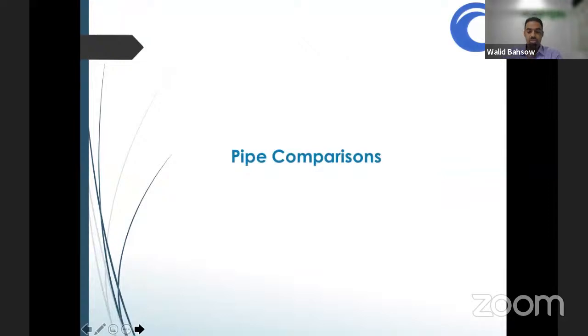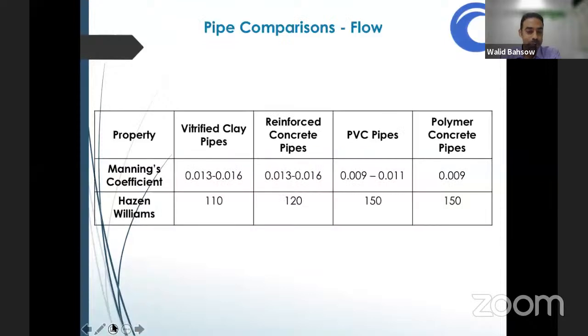So we come to an interesting, I hope, part where we compare different types of pipe materials. Here we have the Manning's coefficient, the Hazen-Williams value, for 4 types of pipes. You have the vitrified clay pipes and the reinforced concrete pipes. You can see that the Manning's coefficient deteriorates with time. It usually starts around 0.013 and can go up to 0.016 or even higher. PVC pipes have a better Manning's coefficient. And for the polymer concrete pipes, it's 0.009.